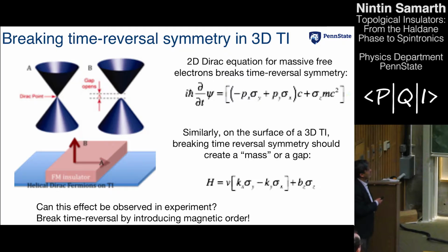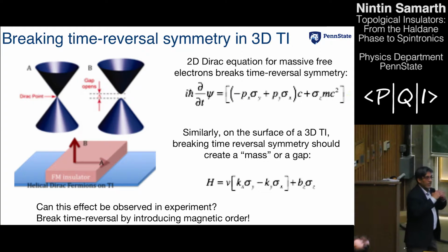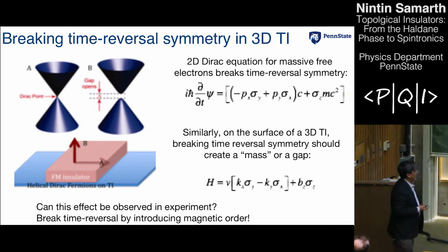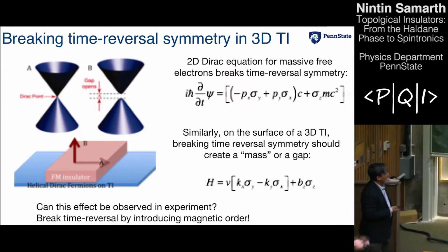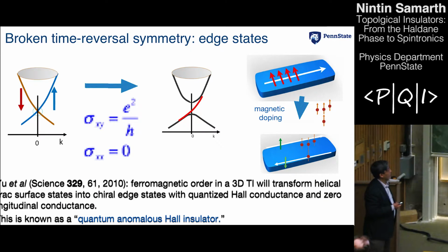So in other words, it looks like a mass. And what happens is that instead of this Dirac point, you get a gap opening. Now this is fundamentally different from the hybridization gap. This is created by the breaking of time reversal symmetry. And one question is, can this effect be observed in experiment? People have tried to do this by breaking time reversal symmetry by introducing magnetic ordering into a sample.